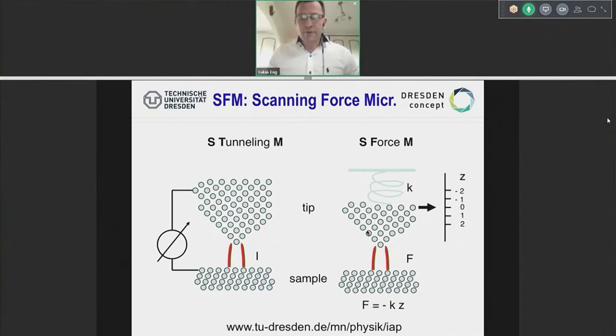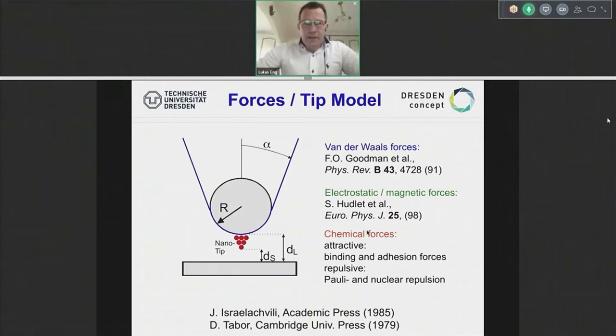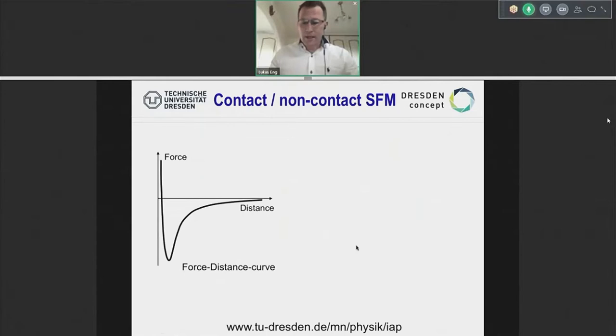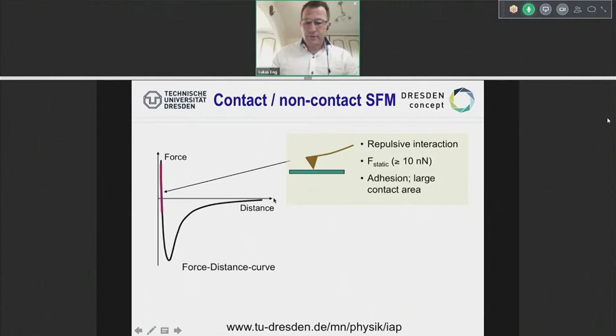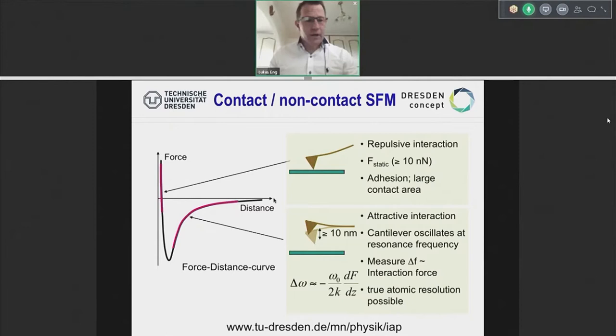The funny thing about AFM is that we have the possibility to look at chemistry at different force length scales and force interaction schemes. For instance, if you go for short range forces, it's a chemical force. That's exactly what makes bonding, strong energies, typically 3-4 electron volts at bonding sites. If you go a little bit further away, electrostatics, magnetics, you can also access the local chemistry through other means like Kelvin. I would like to show first two examples for chemical force interactions, done either in the repulsive regime or in the attractive regime of your force curve. Both regimes are very good for working on it.